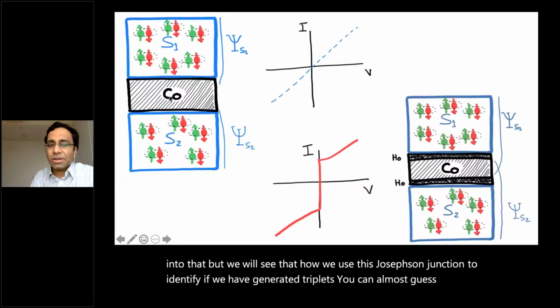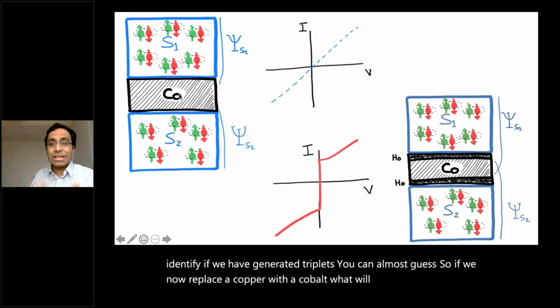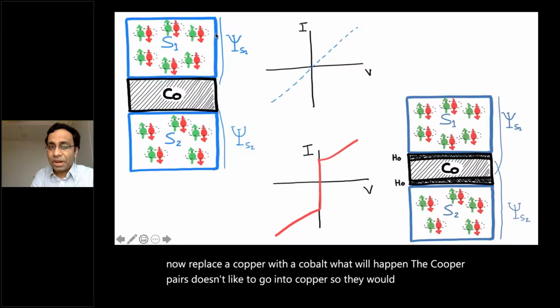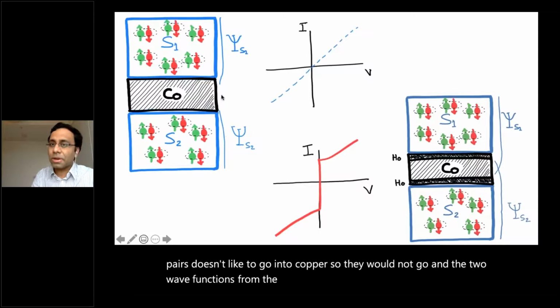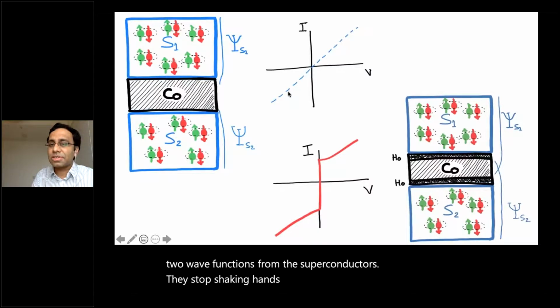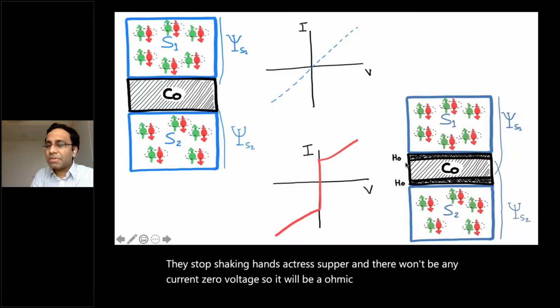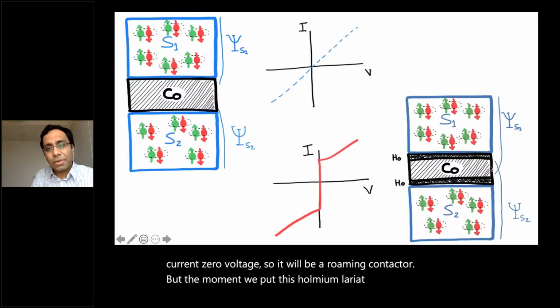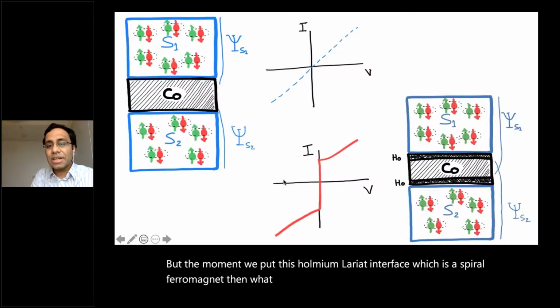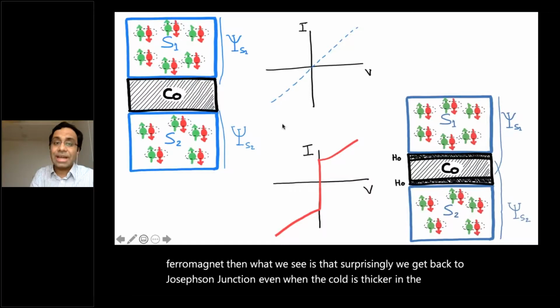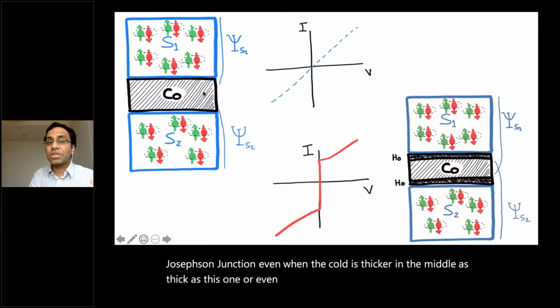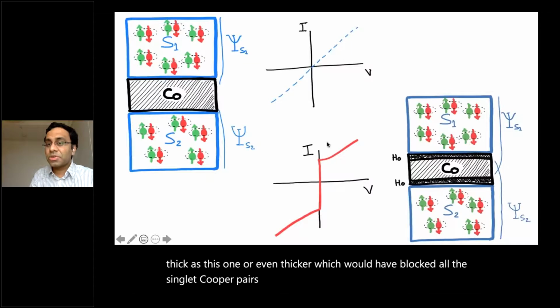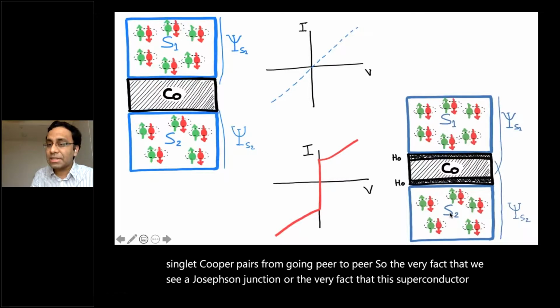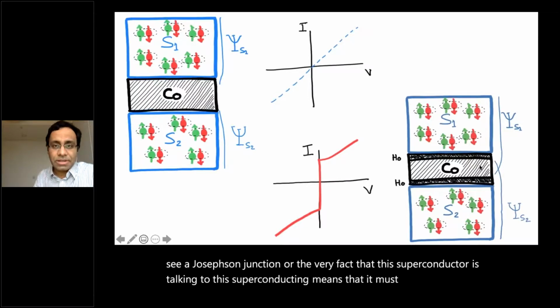So if we now replace the copper with cobalt, what will happen? The Cooper pairs don't like to go into cobalt, so they would not go. The two wave functions from the superconductors stop shaking hands across the cobalt, and there won't be any current at 0 voltage. So it will be an ohmic conductor. But the moment we put this holmium layer at the interface, which is a spiral ferromagnet, we see that surprisingly we get back the Josephson junction, even when the cobalt is thicker in the middle, as thick as this one, or even thicker, which would have blocked all the singlet Cooper pairs from going from here to here. So the very fact that we see a Josephson junction, or the very fact that this superconductor is talking to this superconductor, means that it must be mediated by triplet pairs.